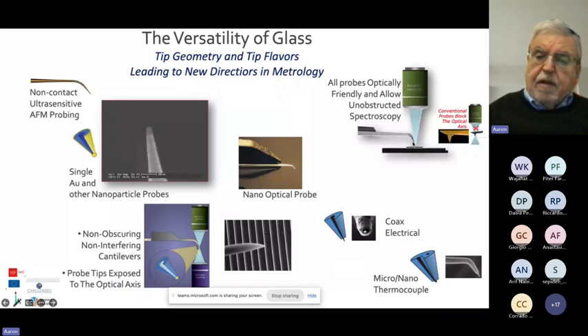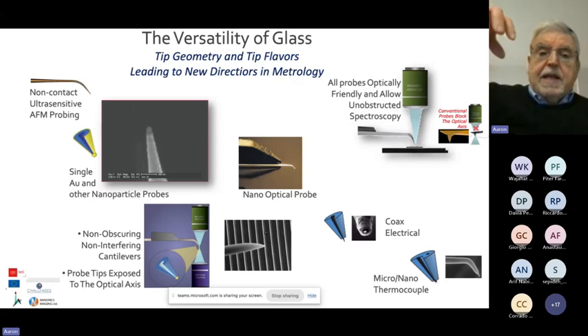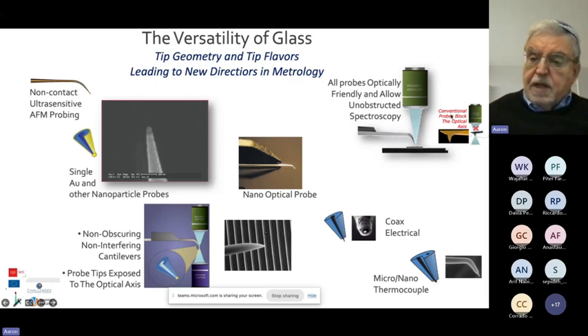The cantilevering of these probes is such that they do not block any of the light from the lens above. So this system of AFM is totally integrated into standard optical microscopy. Most AFMs don't have standard optical microscopes. They are blocked by their scanners from the top. And for that matter, most silicon probes don't allow light from the top either. So for semiconductor analysis, really this methodology that we've introduced into this system in the ERC is actually very good, okay?